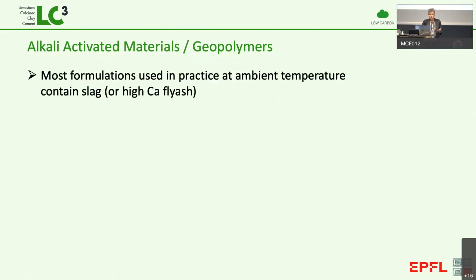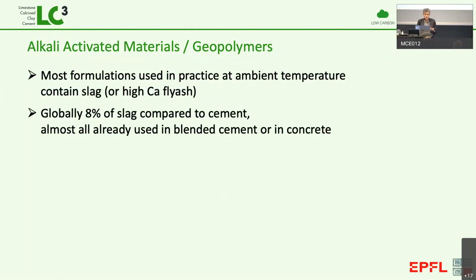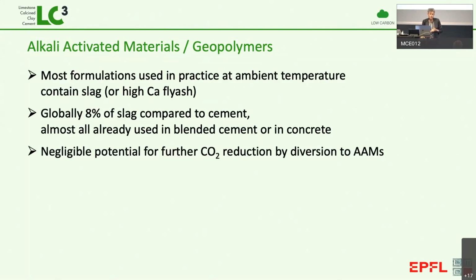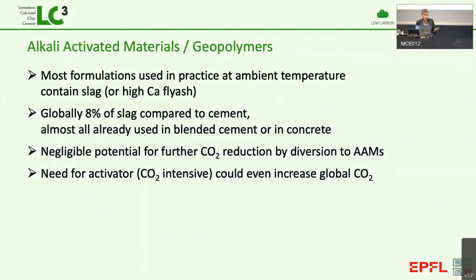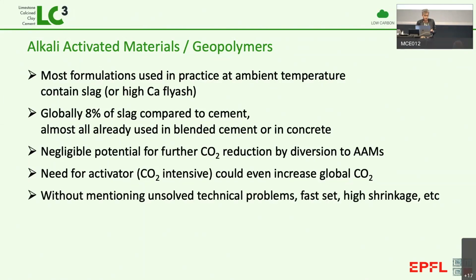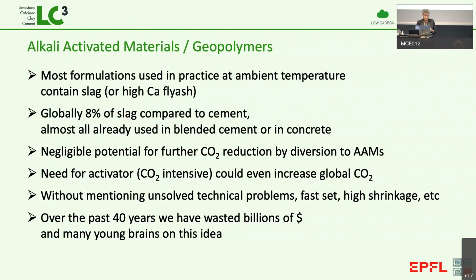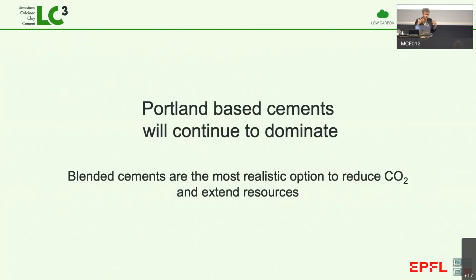Well, the long and short of this is that basically they use these substitute materials, which, as I'm going to tell you in a few seconds, are in short supply. And therefore, these are already used in cement. So again, we can have no gains here. And in fact, overall, we might have a loss because we have to produce the alkalis to activate them. And that's without talking about all the technical issues associated with these materials. So we have to face the fact that this Portland composition is going to dominate.